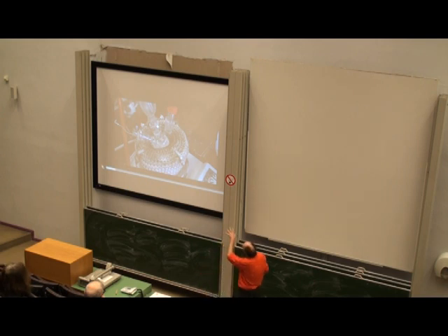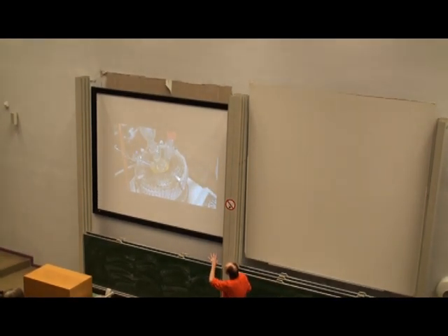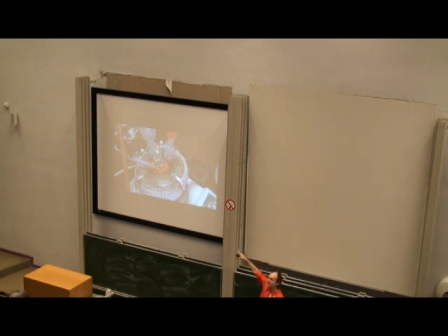And so at a certain point, there will be the injection. There it is, and immediately this solution turns from just transparent to yellow. This is the initial formation of the nanocrystals. And as the reaction proceeds, you see that slowly the color changes. It was yellow in the beginning, which means that you only absorb blue light. Now it's already orange, meaning that the solution starts to absorb also green light. It's slowly turning into red, so we're also absorbing the yellow light.